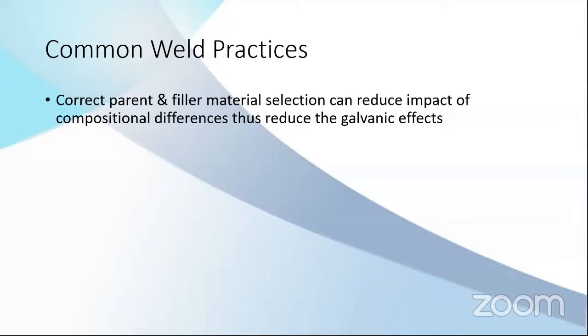This is common welding practice. This is what I normally check in the welding specification. It's better to select the correct parent and filler material. This is more important for the first one, preferential weld corrosion, so we need to minimize the galvanic effect, so the weldment does not experience faster corrosion than the parent material.